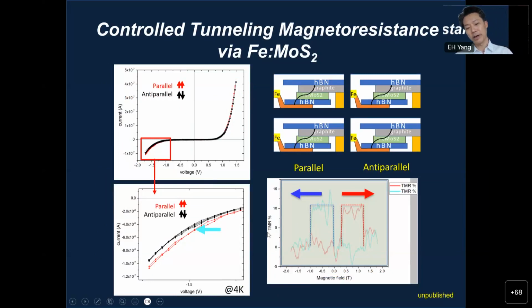The y-axis is the tunneling magnetic resistance, which can be controlled by applying this magnetic field, sweeping from negative to positive. So let's look at this cartoon shown on the top right. First, look at the arrow here. The magnetic pole direction on this iron-doped molybdenum sulfide and this iron, the hard magnet, is the same. Then you have a high current. High current means a lower resistance. That's here. Please look at this cursor here.